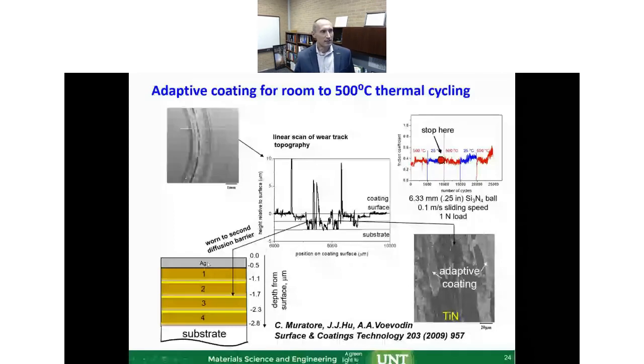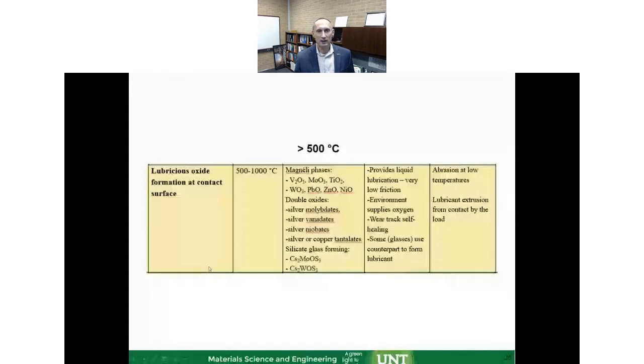If we go higher than 500 C, that silver will get out very quickly, even with diffusion barriers, and we need to have something else. And now we're moving to the world of the oxides. At 500 C in air, the chalcogenides or carbon, or even the soft metals, become too soft to work, so they become not a very enduring mechanism. So we need to have oxide-based chemistry working, because then we're not fighting nature; oxides naturally form. So the trick is how we can guide this oxide formation to the ones which we need.